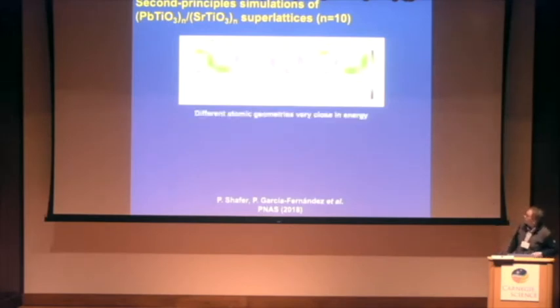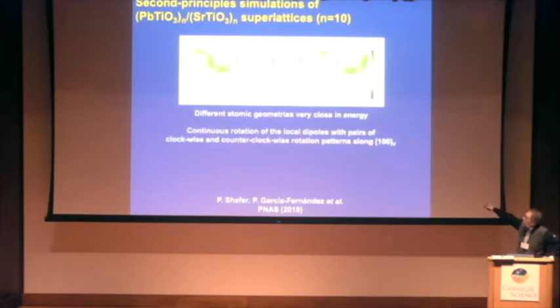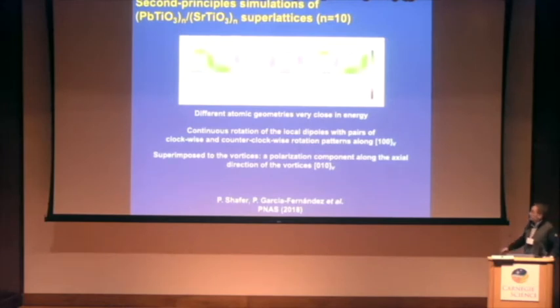So we could identify different atomic geometries that were very close in energy. In particular, the three that I am plotting here are degenerate in energy. So we do observe a continuous rotation of the local dipoles with pairs of clockwise and counterclockwise rotations as before, but superimposed on this structure, we were able to detect a component of the polarization pointing in the direction perpendicular to the screen, so in the direction of the axis of the vortices.